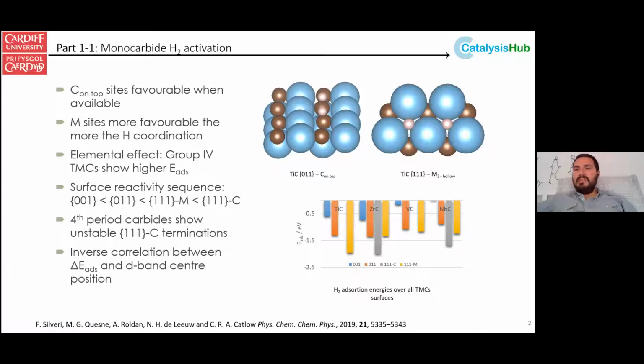When you cut the surfaces for these materials, the low index surfaces have either metal carbon layers or mixed surfaces with both carbon and the metal. The first thing we did was look at hydrogen loading. We looked to see where hydrogen bound on these surfaces. When we look at the low index surfaces, we see that depending on the surface geometry, we get very different adsorption modes.